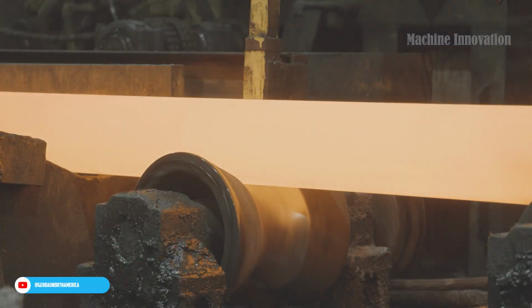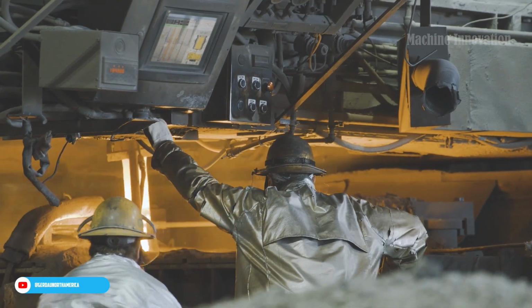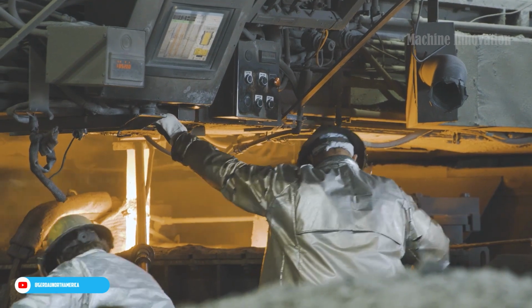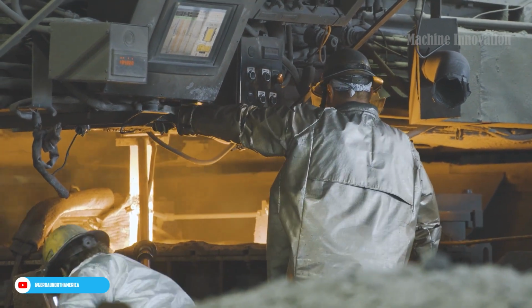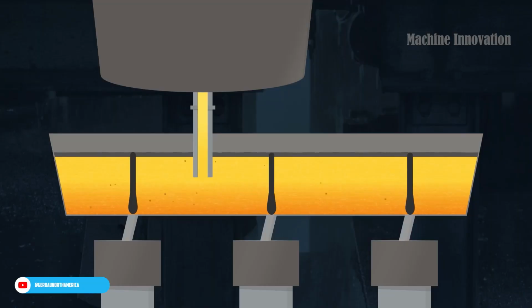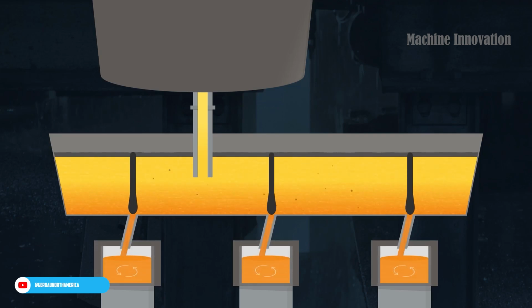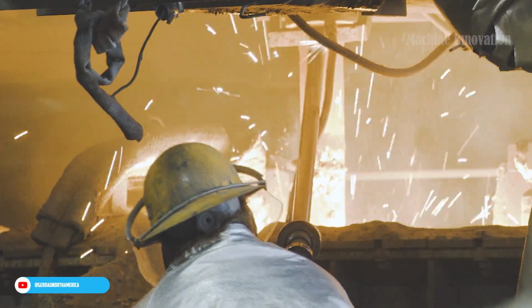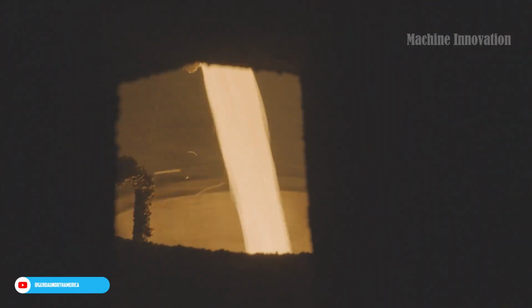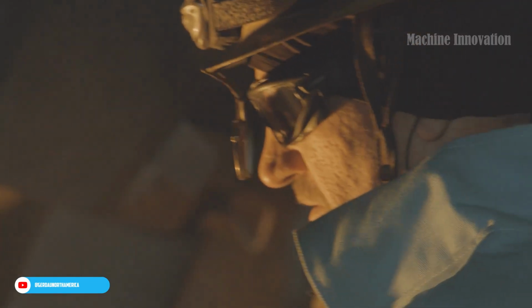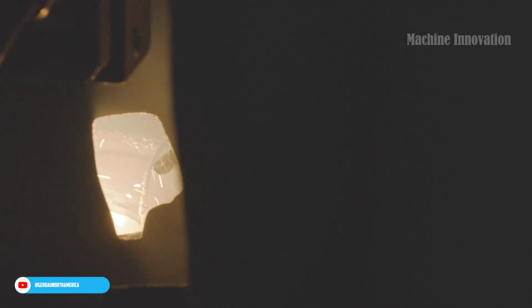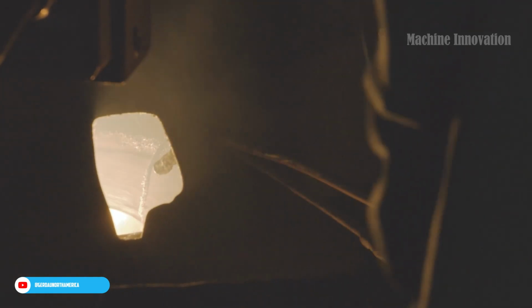In the ladle furnace, more alloys are added to the molten steel to meet specific customer requirements. The mixture is carefully stirred, allowing the alloys to dissolve evenly. Argon gas is used throughout the process to encourage homogenization and aid in removing non-metallic inclusions. The ladle furnace stage is crucial, as it ensures that the steel achieves the desired chemical composition and meets the stringent standards required for various industrial applications.